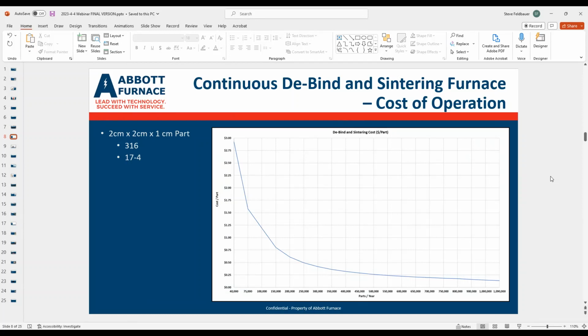Just to give you an idea, for this model that we put together, we went out to actual producers. We collected data on actual equipment for both the vacuum and the continuous. So what you're seeing here is a model that we've put together based on real data. And we've been accurate enough that we're able to predict our cost per load within about $50 for a vacuum furnace, and likewise for a continuous furnace. So the model is being used for folks in pricing, and it seems to be very accurate. I'll mention some of the assumptions that we've made in terms of cost, and we've tried to be very conservative and run on the high side of the cost so that you can trust the values.